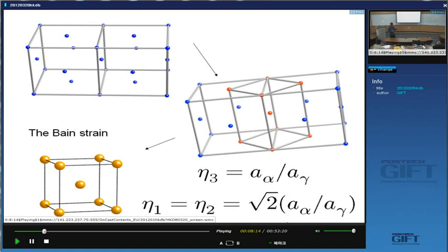and see whether this deformation can produce an invariant plane, and at the very least can it produce an invariant line, because that's the minimum condition for martensitic transformation. Yeah, you remember that from the last lecture, that to get martensitic transformation you must have at least one line undistorted and unrotated.